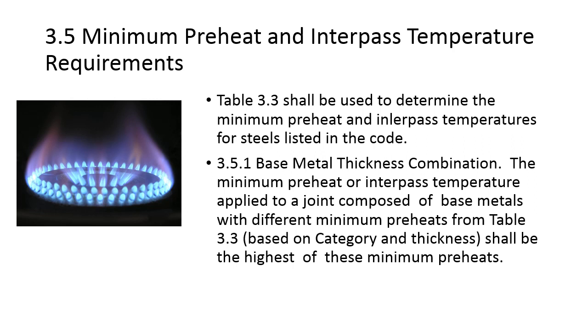Table 3.3 gives you the minimum preheats, and this is based on material and thickness. So if you've got a really thick piece of group 2 material that's 3 inches thick, you're probably going to need to preheat it, because that thing's going to act like a heat sink and suck all the heat out of your weld. And if you don't have some heat in there, you're going to possibly have cracking issues.